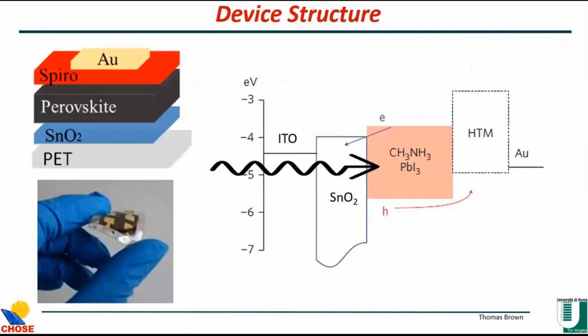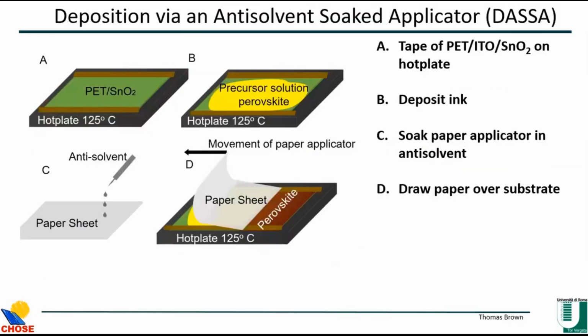So this is the device structure we've been using. Polyethylene terephthalate substrate, then ITO. This is the SnO2 layer where you can inject electrons, but it blocks holes. Then the perovskite layer where the photo absorption happens. There's a HTM, spiro-OMeTAD, where it collects holes, but there's a barrier for electrons. So this is the standard structure for flexible cells, and these are all at low temperatures. And this is the final cell, a photograph of the side of the final cell.